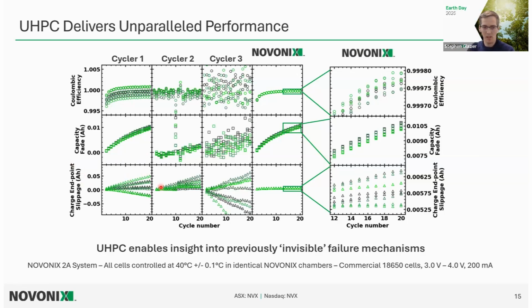But really where UHPC, where this accuracy comes in, is measuring this charge endpoint slippage cycle metric. All of the other cyclers in the battery field have a slight bias between charge and discharge, so it's always slightly overcounting or always slightly undercounting. What that means is this Coulombic efficiency value can never be quite accurate. This really shows up in our ability to track that endpoint moving across our capacity axis. Some of these cells are walking backwards, some of them are walking forwards in all of these different cyclers, and you can really only track that with our order of magnitude of accuracy and precision.